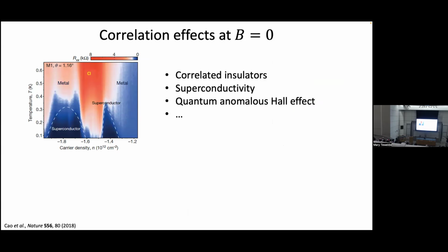I just want to highlight something that I've glossed over, because I could gloss over it, since the previous device was so beautiful and homogeneous in terms of twist angle. But actually, when you're assembling these layers with one another, we're picking them up with some squishy polymer, and remember, these are like saran wrap. So you pick them up, push them down against each other, and this introduces generally uncontrolled strains and twist angle variations, and pretty much every single sample that you fabricate is going to be a little bit different from another. And that makes it very hard oftentimes to figure out what is the intrinsic physics, what's really controlling what's going on at a microscopic level.